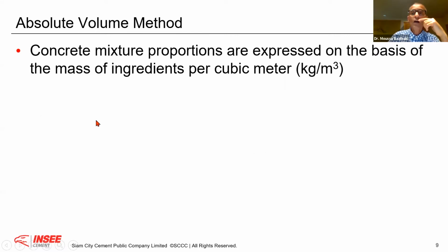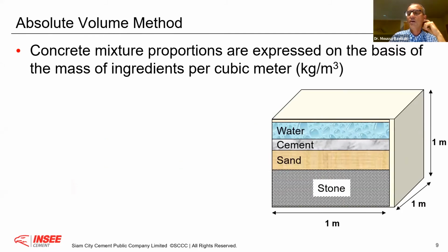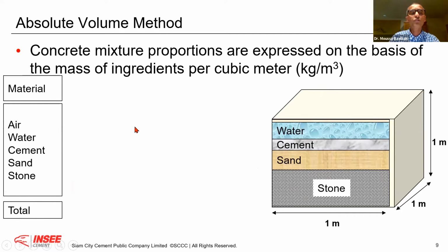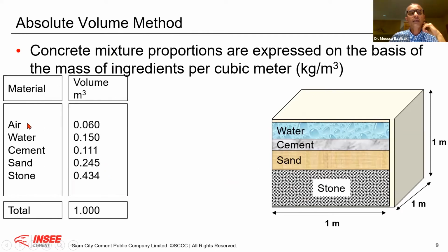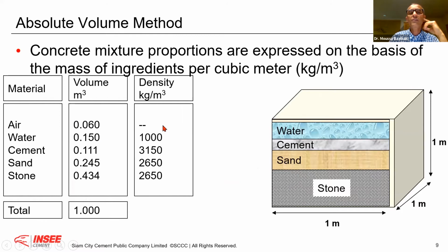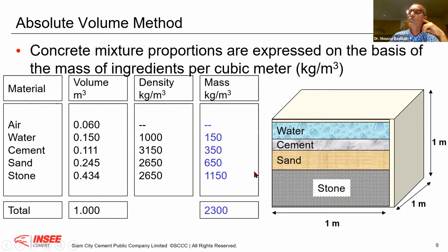Now, a concrete, as I said, we express everything per cubic meter. Therefore, if I have, for example, 1 cubic meter of concrete with aggregate, with sand, with cement, with water, each of them will occupy a certain volume. Say air will have 6% of air. This will be 60 liters. Water 150 liters. Knowing the density of each of them, I can get the kilogram per cubic meter. Therefore, I can get for 1 cubic meter of concrete the constituents in kilogram per cubic meter. Therefore, always when you are designing a concrete, you should come up at the end with kilogram per cubic meter. Okay, that is important.